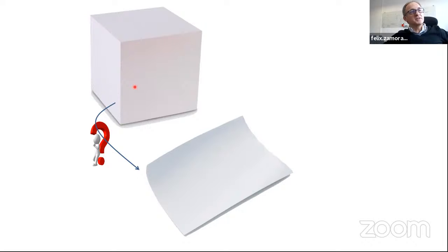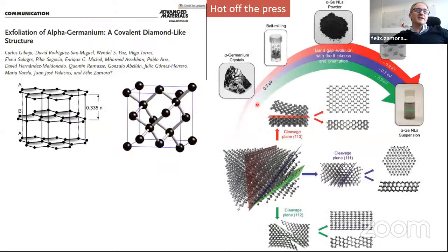So if you start with diamond, the question is, can you produce nanolayers? And just to show you something coming from the press, we recently proved that it is not strictly necessary to start with a layered material to end up with a 2D nanostructure. And here we demonstrate that it is possible to work with a diamond-like structure. This is alpha-germanium. And using chemical forces, we were able to delaminate via specific planes that I show you here very briefly, and end up with suspensions containing these small nanolayers of alpha-germanium.